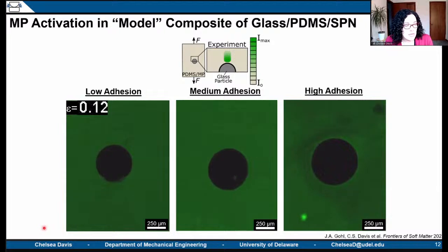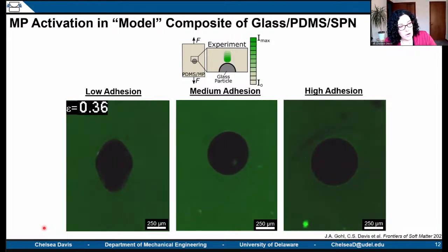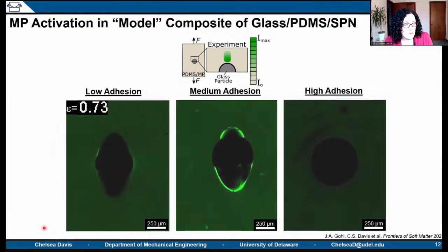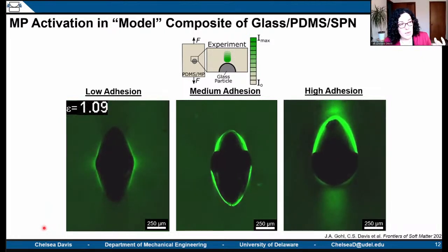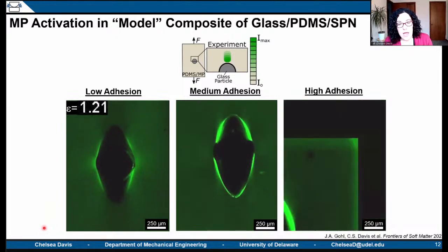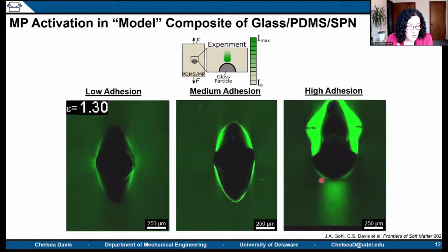So low adhesion is something, if I'm going to quantify it, that occurs where failure between the matrix and the particle is going to occur at single percent strains. Medium adhesion is where we observe the interface stays formed long enough so that you get these jet-like debonding events. You store enough energy in your system so that when the interface fails, you observe really large deformations and instabilities within your material. And then for high adhesion, it was observational, right? But it came down to we never observed interfacial failure. We actually got cohesive failure in our matrix before we observed separation of our interface.